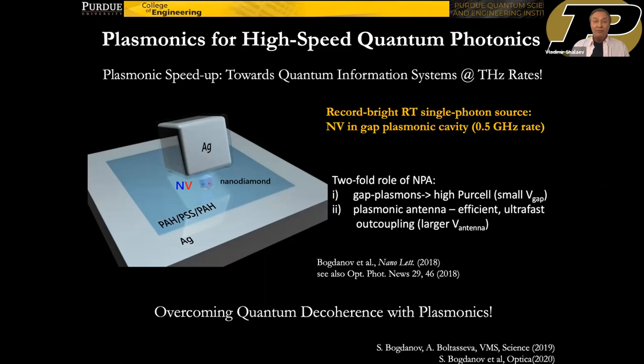The role of the antenna in this case is twofold. Because of the gap plasmon enhancement, if the gap is small, you have this strong gap plasmon enhancement, this is Purcell enhancement. But the antenna itself, the size of the cube, should be relatively large so that it would outcouple photons at very high rates, faster than the decoherence rate and faster than the rate with which plasmons decay. So if you accomplish that, you would have a loss-free, very efficient source of single photons, which would be potentially immune to decoherence. So that's the idea.